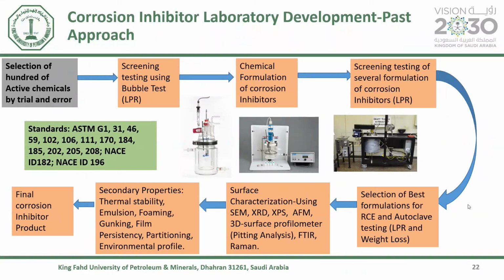And then from the screening stage, you move to selection of the best formulation using more severe conditions, where we can use rotating cylinder electrode and autoclave testing. Sometimes we use a flow loop and jet impingement just to simulate very high shear stress. Then you can also carry out characterization if you want to understand whether there is pitting. You can use a surface profilometer to analyze the pitting, and also other surface characterization tools. Then to make sure the corrosion inhibitor will perform well in the field, you also do what we call secondary property testing, like thermal stability, emulsion, foaming, film persistency, partitioning. And for applications like offshore, you have to be sure that your inhibitor will be non-toxic to meet some strict environmental guidelines.